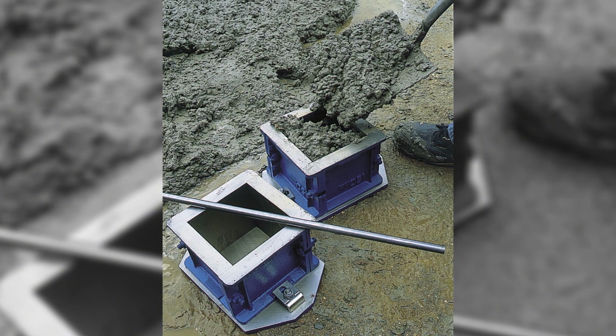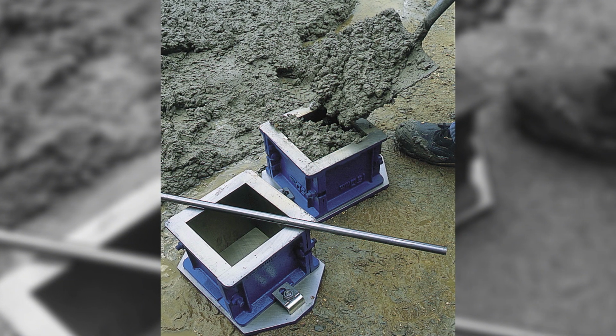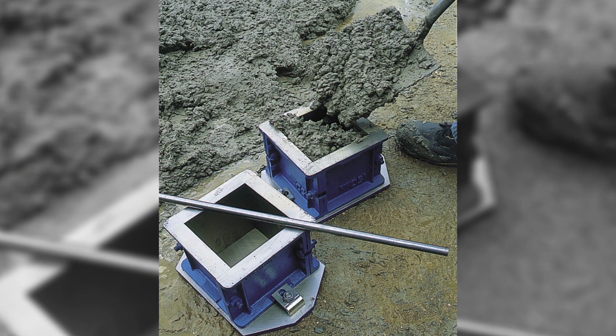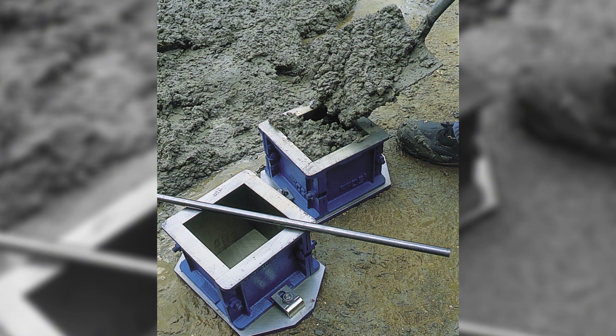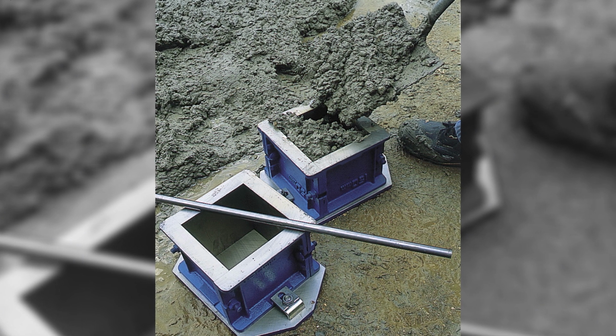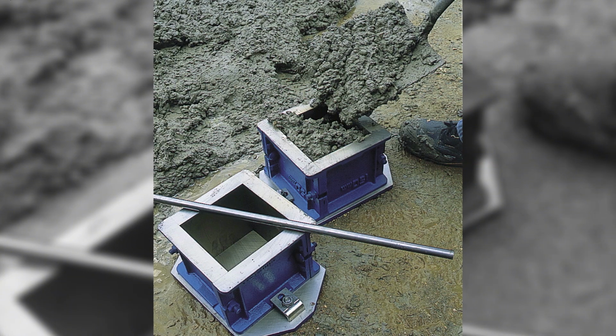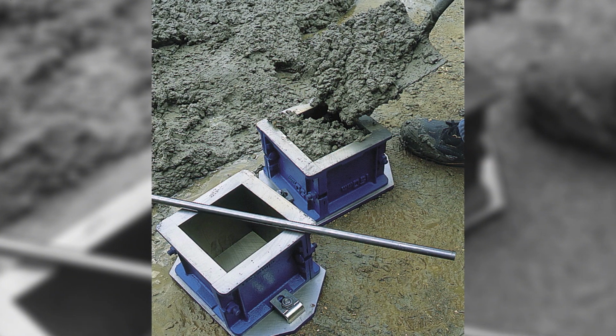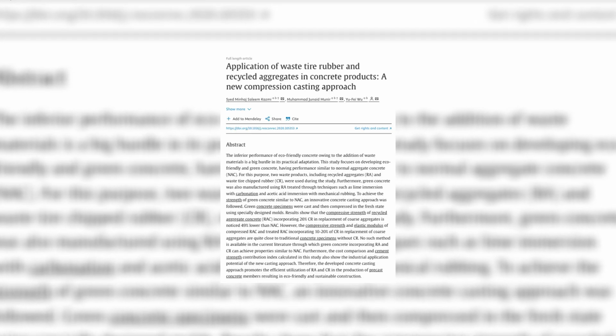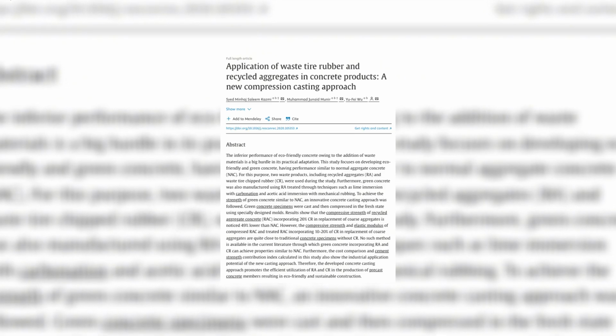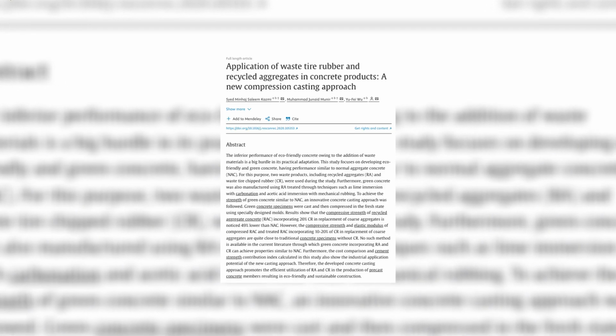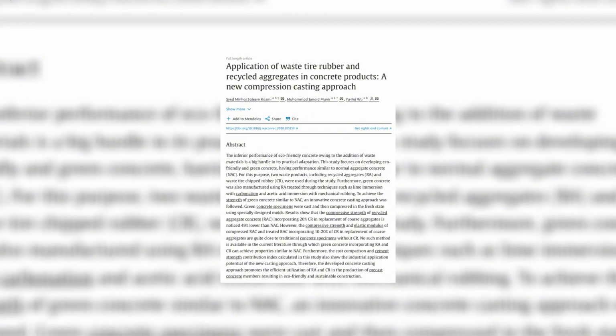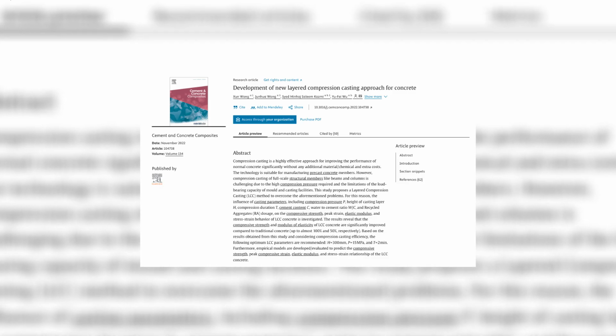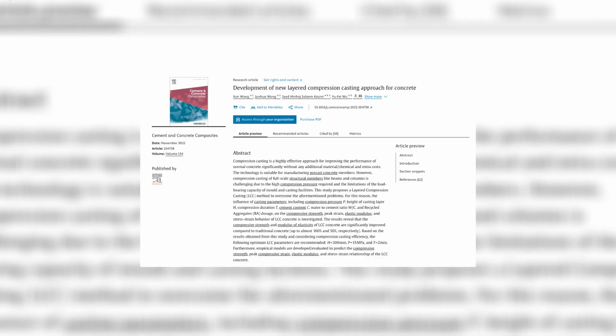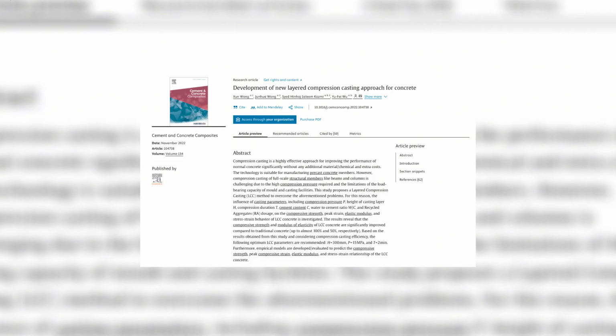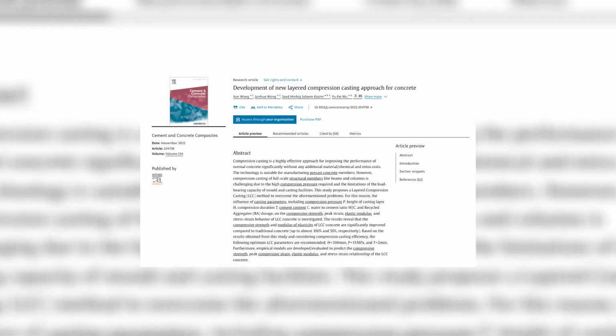If a smaller quantity of cement can produce concrete with the same required strength, less cement may be needed for a given component. Alternatively, manufacturers may be able to use lower quality or recycled aggregates without accepting the usual reduction in performance. Researchers have already tested compression casting with materials including recycled concrete aggregate, waste rubber, desert sand, and recycled powders. In other words, the process does not make cement carbon-free. It may allow engineers to get more structural performance from each kilogram of cement they use.